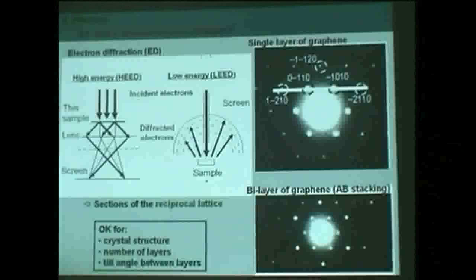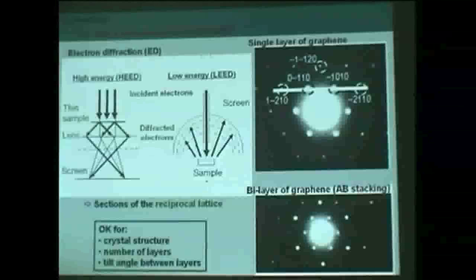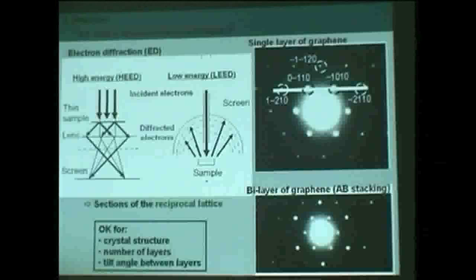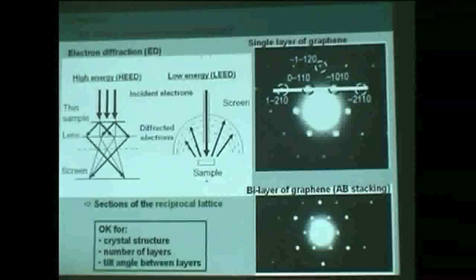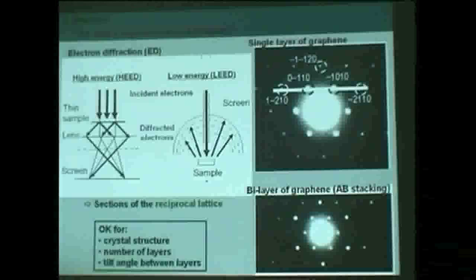What does it tell us? It tells us that the electrons diffracting by one layer and the other layer have interfered, and as a consequence of this interference, the intensities of a given dot have been modified. We could go to complex calculations to explain that in detail, but it tells you that electron diffraction allows you to differentiate between a single layer and two layers, even though they have exactly the same crystal structure.